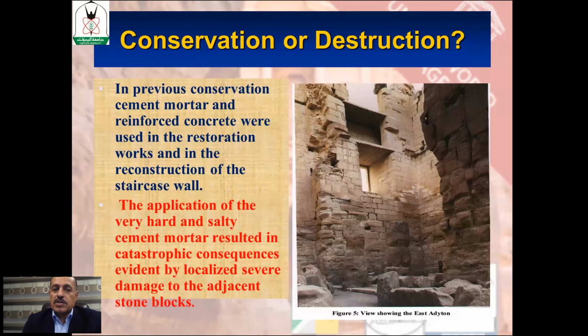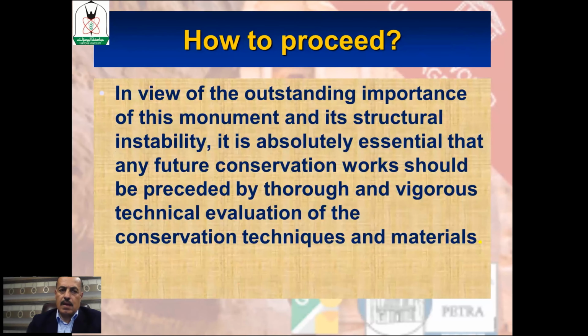Now, the application of the very hard and salty cement mortar resulted in catastrophic consequences, evident by localized severe damage to the adjacent stone blocks. Because of the importance and because of this bad experience, our approach for dealing with this monument was a very cautious one.